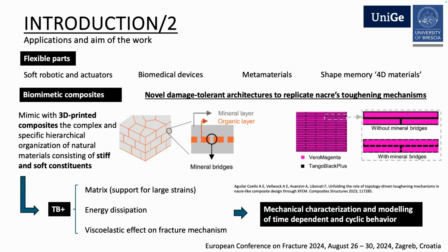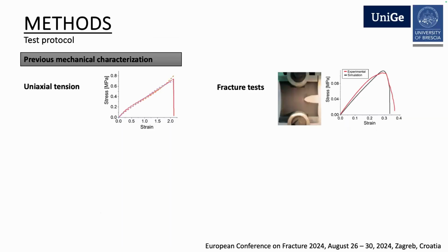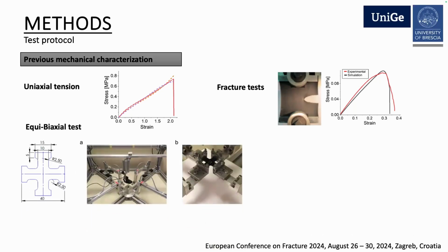And this is why we investigated the behavior of this material, considering in more detail time-dependent and cyclic behavior. So the final goal is to improve the accuracy of the models that we have previously developed of these composites. The material has been studied before, so we have already carried out uniaxial tension, some fracture tests on single-edge notched specimens, and equibiaxial tests, which were carried out on an in-house biaxial test rig that we have available in Brescia and that we designed a few years ago specifically to test soft materials.